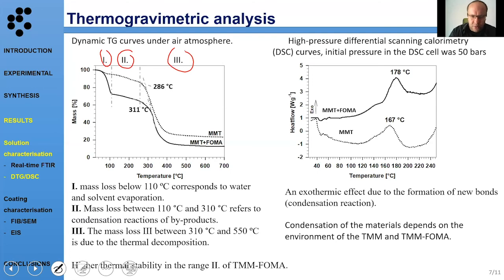The first one, of course, corresponds to water and solvent evaporation, but the most important is the second one, which is related to the condensation reaction between all species which are present in our solution. And the third is the thermal decomposition. However, if we compare the coating without and with perfluoroacrylates, we can see that the coating with perfluoroacrylates is more stable. So that means when we add these molecules in our solution, we change the thermal stability.